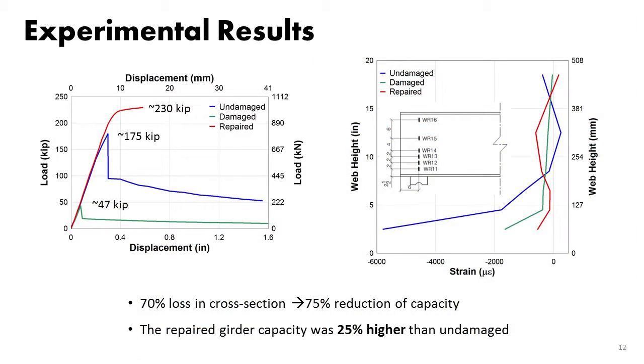These are sample load displacement curves. The blue one is the benchmark. This sharp drop is because of buckling. And for the sample with 70% corroded section reduction, we got a 75% reduction in capacity. The green one is showing that. And the red one is the repaired one. You can see this plateau is because of the flexural yielding of the beam. And we even went 25% over the capacity of the intact beam.